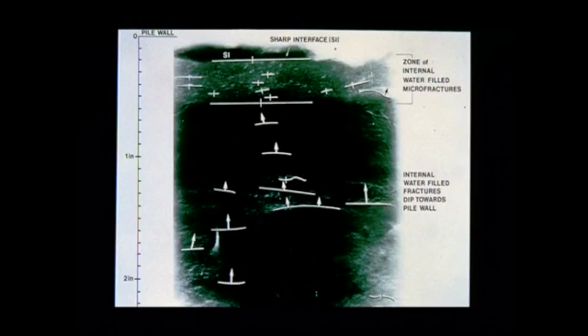Again, I thank Dwayne Bogard for this photograph, but this is what one of the cross-sections looked like in an X-ray. We're viewing a cut section of soil surrounding the pile in a direction parallel to the pile wall. We're looking parallel to the pile wall. The soil near the microfractures, or shear surfaces, had higher moisture contents than the masses of soil in between them, and the lighter colored soil up here near the interface was considerably denser than the darker soil. This is just like looking at an X-ray of a bone. The bone is light, the flesh is dark. So the lighter colored material is denser than the darker material.